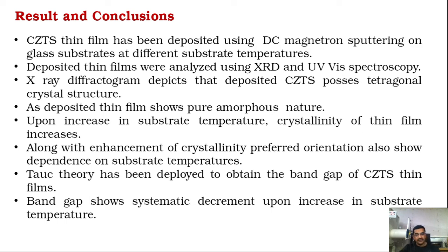Along with this, by using the Tauc plot, I have obtained the band gap of the CZTS thin film, and that plot shows a systematic decrement in band gap with increase in substrate temperature. This is all about the investigation which I have carried out.